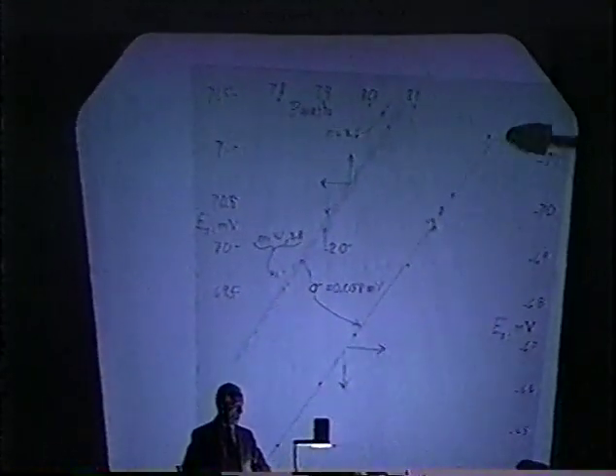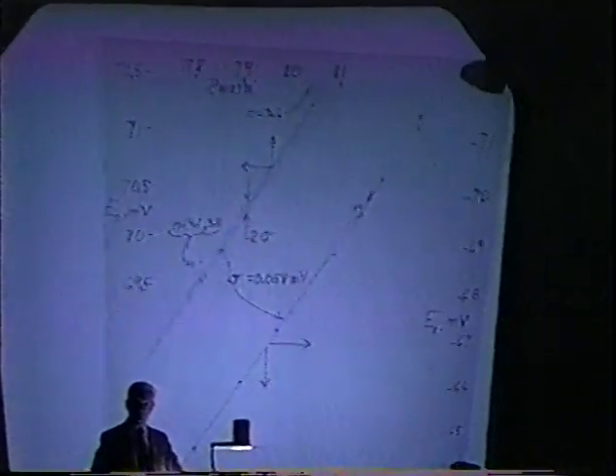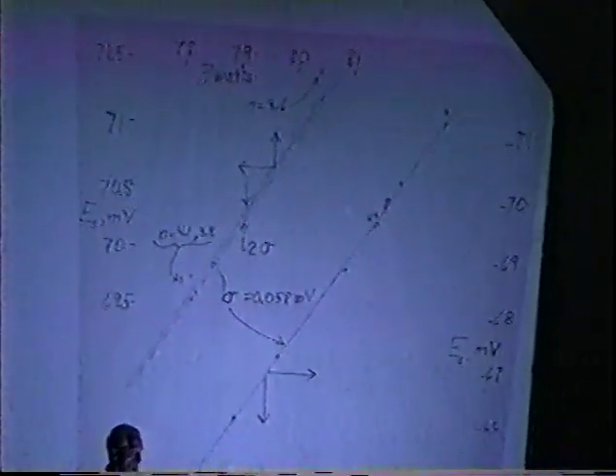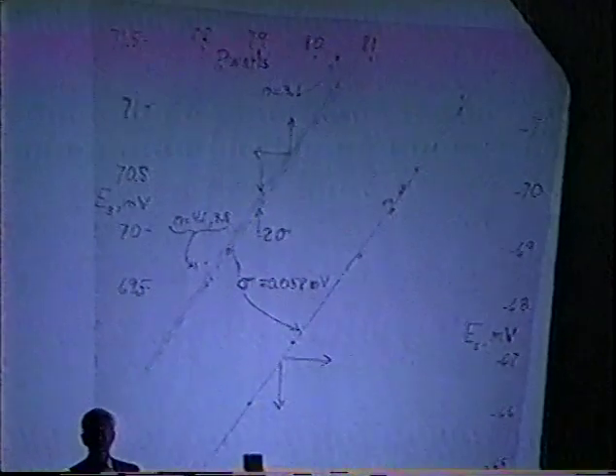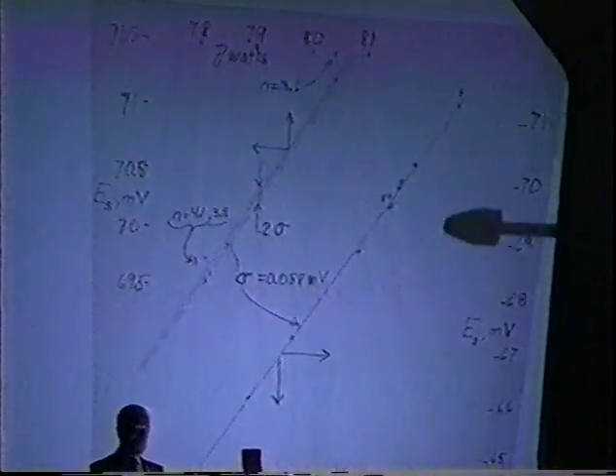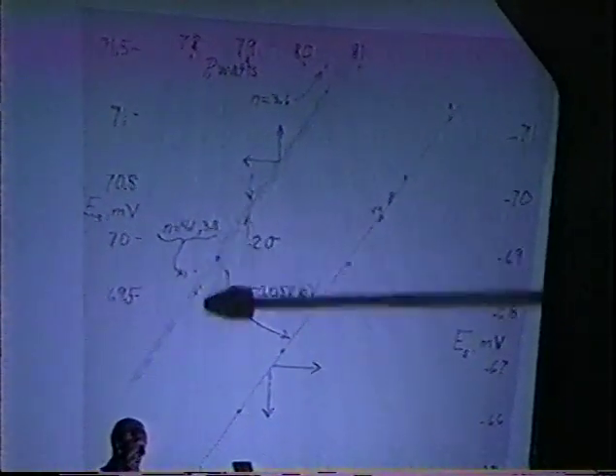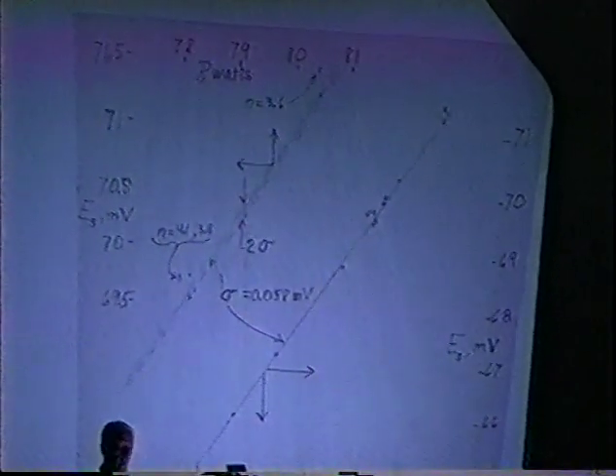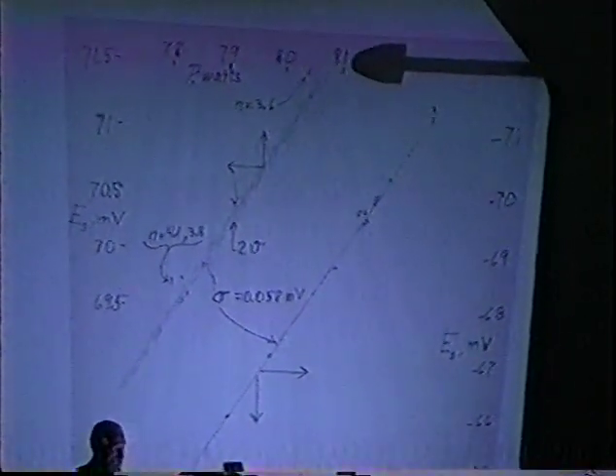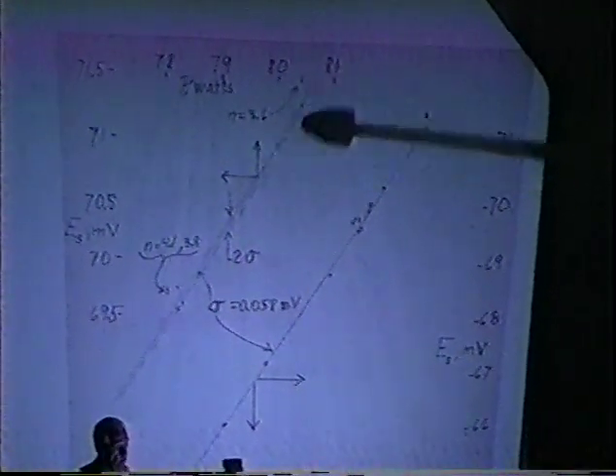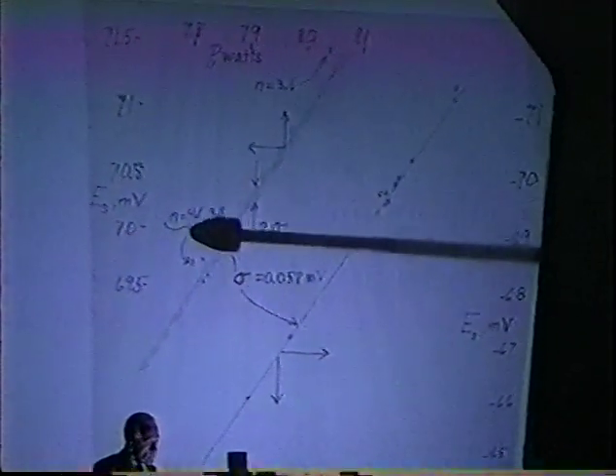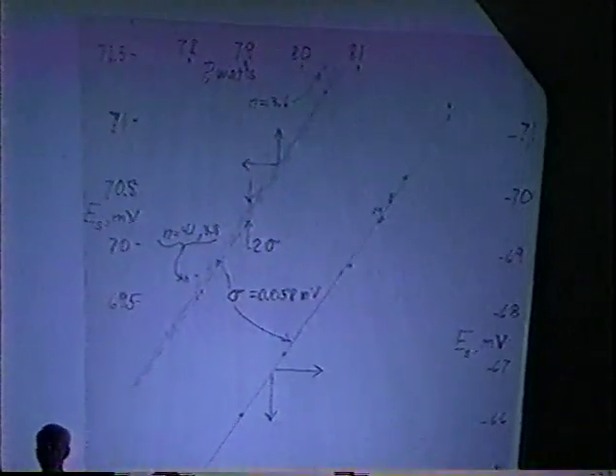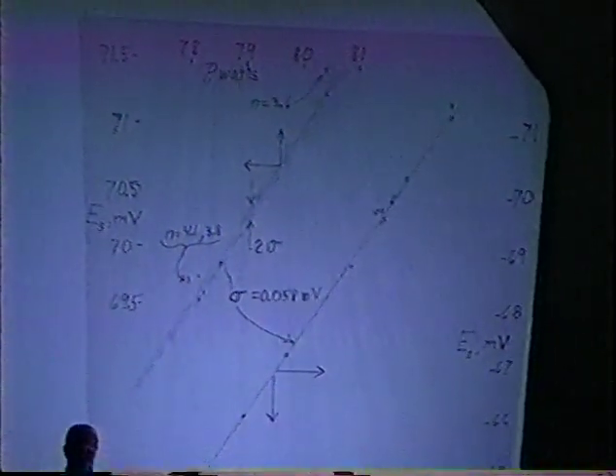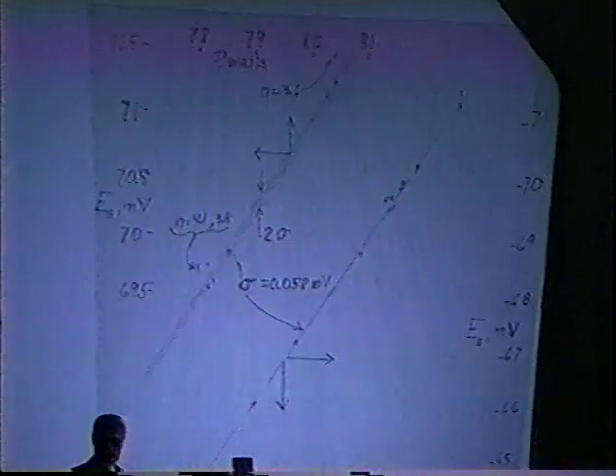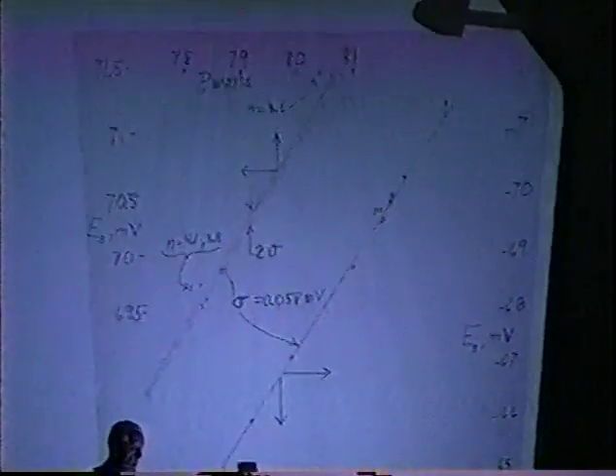Here is the calibration curve. The X's are in fact power runs. The calibration curve has a sigma value of the order of 0.08 millivolt. And this band represents, therefore, 2 sigmas, both above and below the line. The interesting power points are the X's over here. And you can see 3.6 sigma value for this one, and this one 4.1 sigma value. I call that marginal. It looks okay, but I prefer to feel that. I just show you this because this shows you exactly how I've done things.